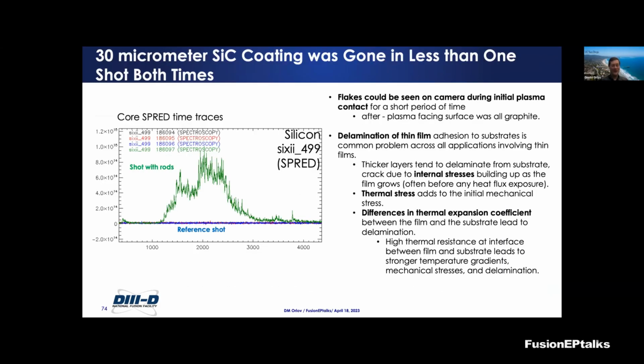The second question is something I can address. On some of those rods that we exposed to the high heat flux, we had the silicon carbide coating, about 30 micrometers. But what we learned after the experiments was that the coating, the way we'd done it, did not work nicely for our experiments, just because different thermal expansion rates of different materials, when you apply the coating the way we did it, caused thermal stresses, and those resulted in a very extremely quick peeling off of the coating material.